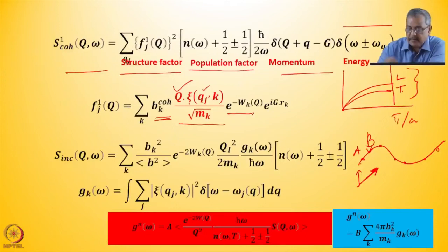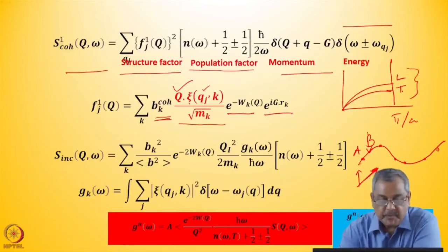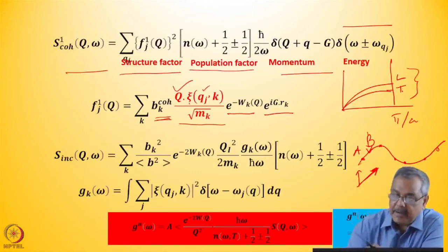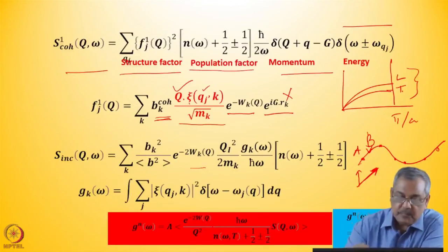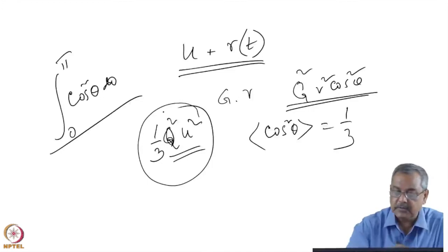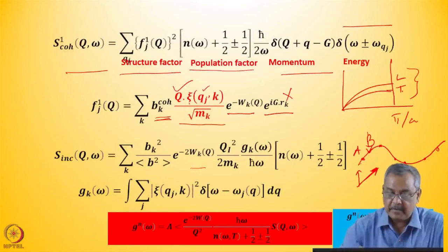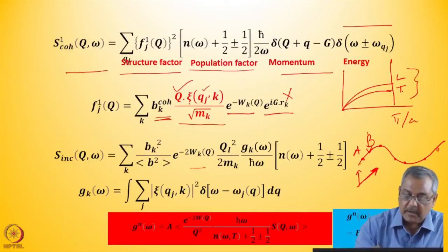After that, you have very simple terms like this is a Debye Waller factor and this is a structure factor. For this incoherent approximation, I am considering each atom is acting independently, so I need to square this. So then this will go away. This will be minus 2Wq. Now q dot xi, I showed you just now, it is 1/3 q square xi square by the same logic by which I did it for calculations in Debye Waller factor.